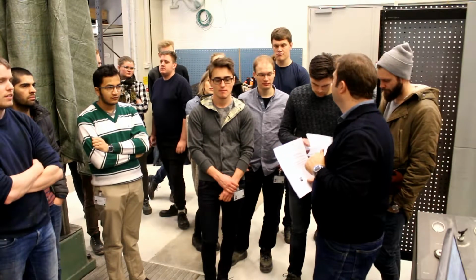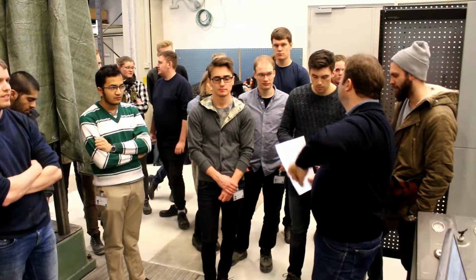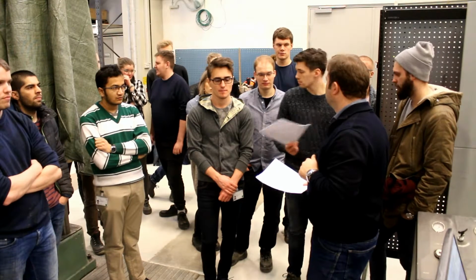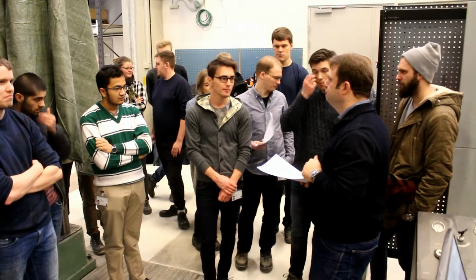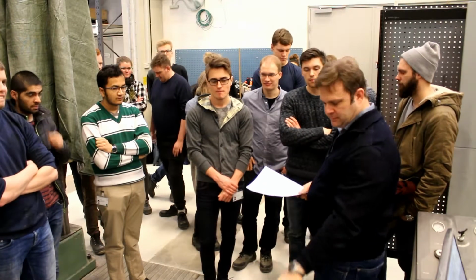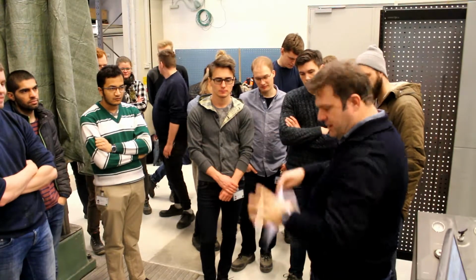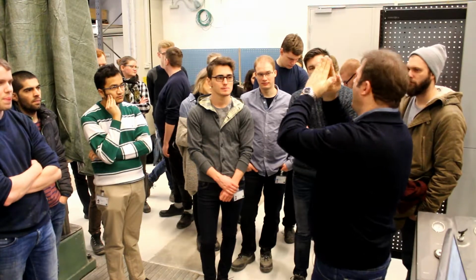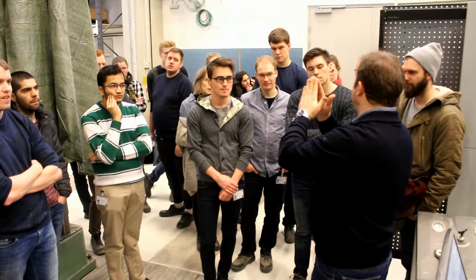How wide do you think we can make that crack before we have zero load? Let's say the fiber is 50 millimeters long. How wide would we have to open the crack for the load to drop down to zero? Have a look. We have zero crack opening at first, and there's a fiber bridging that crack. And we open this crack. How wide can we make it before the fibers cannot carry any load anymore? The fiber is 50 millimeters long. Let's say the crack is 100 millimeters open. Any chance there's any fiber left?